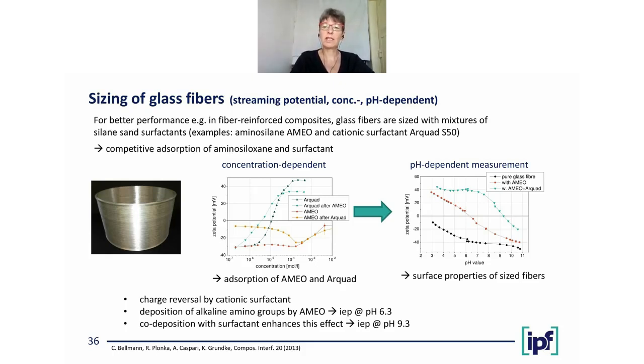And in the image in the center, you can see how the Zeta potential changes if only the surfactant or only the aminosilane are adsorbed, and if they are adsorbed one after the other. And in the pH-dependent measurement at the right-hand side, you see that the glass fiber usually has a very low isoelectric point due to its hydroxyl groups on the surface. If we add the aminosilane, the isoelectric point shifts, so it has a more alkaline behavior. And if we add both the aminosilane and the surfactant, then we get an even higher isoelectric point, and this can ensure better filler matrix interactions with the polymer.